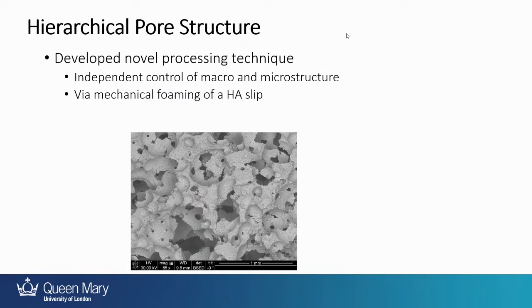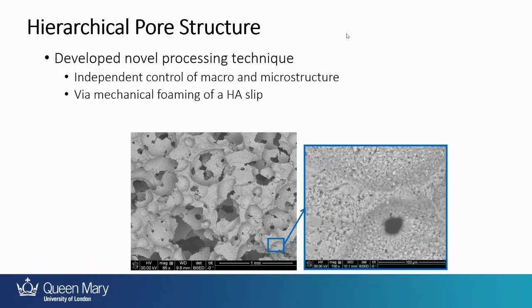So we started looking at trying to develop a novel processing technique that would give us the ability to make porous structures with hierarchical pore structure. So it's not only porous at the scale you can see when you look at it, but the little white struts of the material are actually filled with porosity as well. So this will help to make sure that you'll get nutrient transfer throughout the structure.